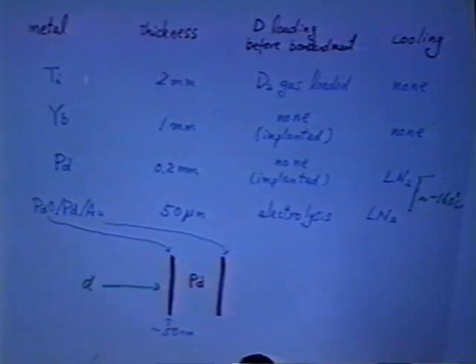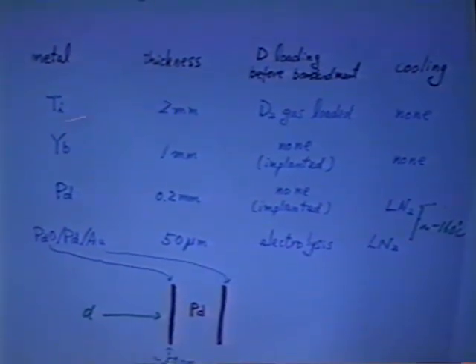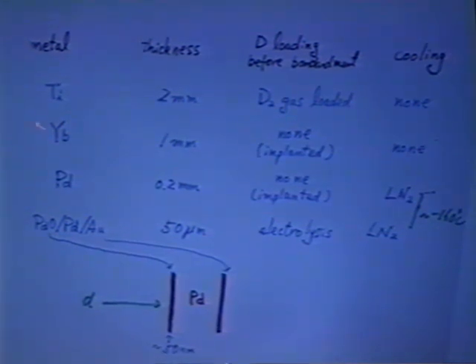So our target conditions were something like this. This titanium and ytterbium was for the data which I reported at the last conference. But this time, we didn't have a cooling system, so we didn't cool it. And the deuteron inside the target is realized by various methods. For the titanium case, just gas loaded. And for the ytterbium and the palladium case, we didn't do anything. Because we are impinging with deuterons, we just wait for enough deuterons to accumulate inside the target, inside the metal.